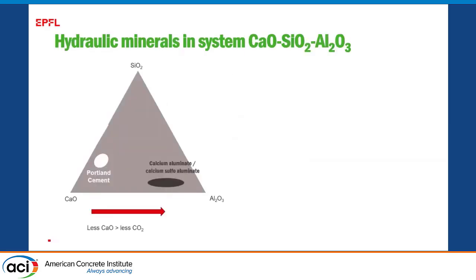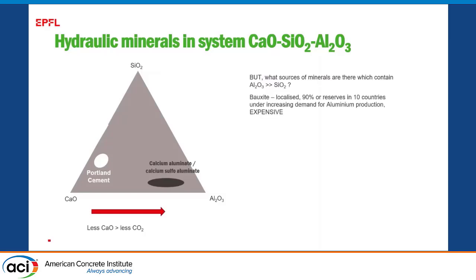And then if we come to that diagram, there's basically these 2 regions where we can produce cement. This region we call Portland cement, and this region we call calcium sulfoaluminates. There's been a lot of hype about calcium sulfoaluminates as a way to lower CO2 emissions because they do contain less calcium oxide, and when you're producing from limestone, less calcium oxide is less CO2. But the problem is you don't just need less calcium, you need a lot higher alumina compared to silica, which means you're confined to using something like bauxite, which is very sparsely distributed, and even if we used all the bauxite we produce today, we would not be able to fulfill much of the cement demand.